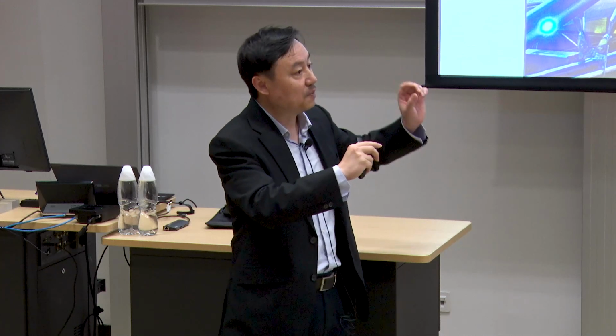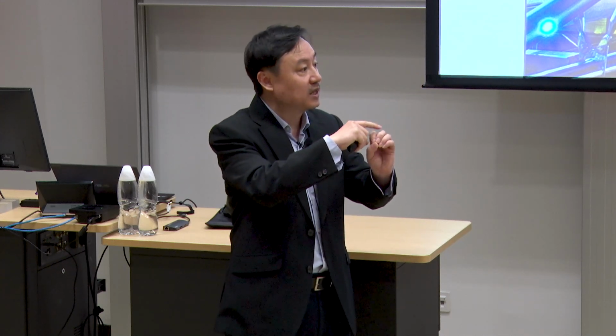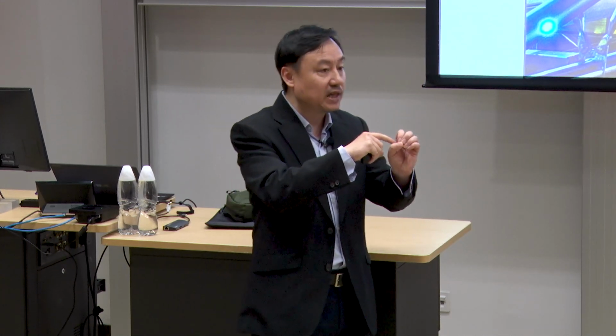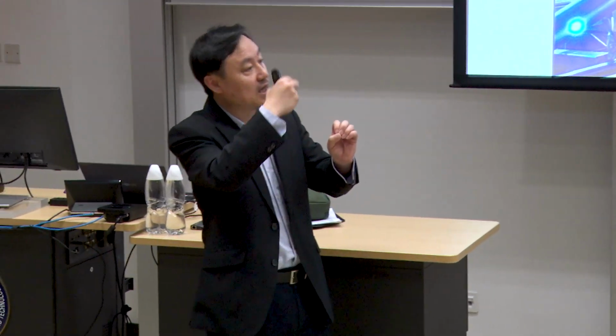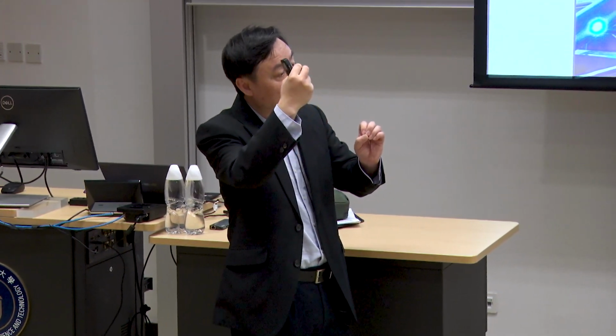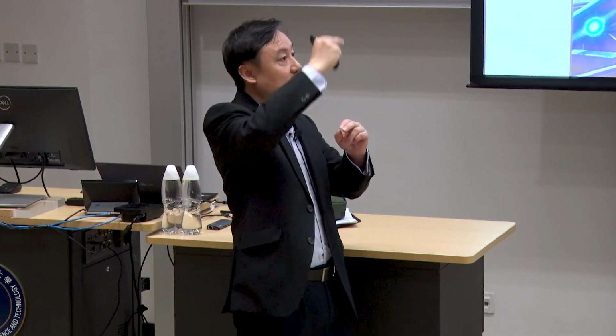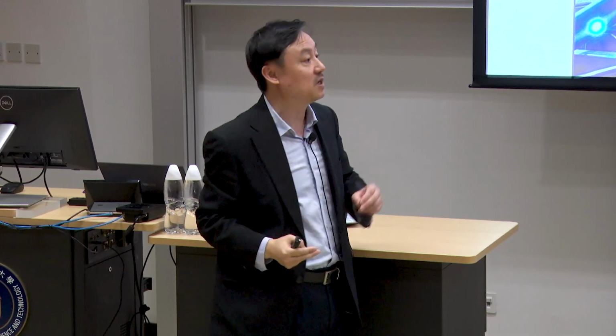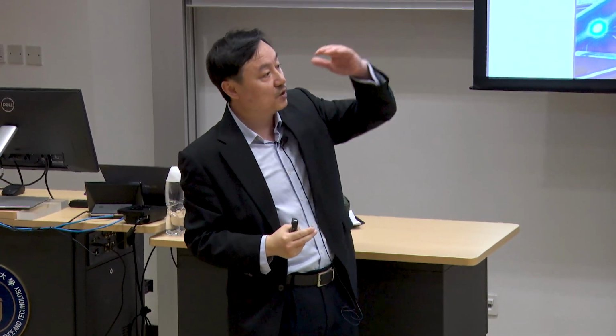So the key difference is the lanthanide complex using lanthanide organic ligands. These organic ligands have strong vibration, but for lanthanide inorganic particles, they have a pretty rigid lattice. So this rigid lattice actually protects this excitation energy. So once it absorbs 980 nanometer, you have this excitation to the intermediate states. So that gives you the protection here.